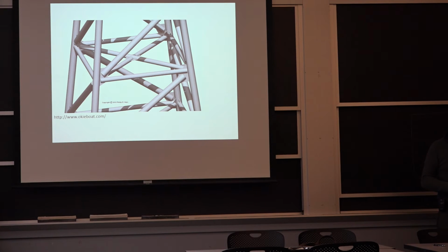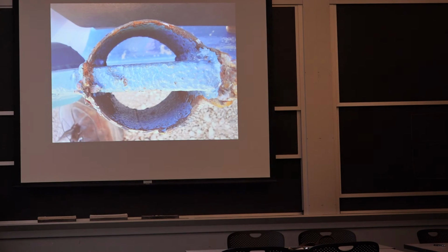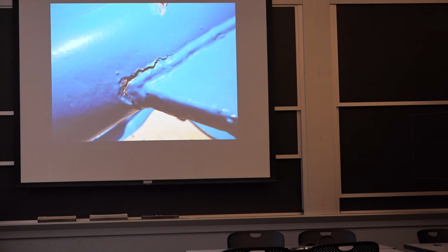Now, the people that put that segment of crane together didn't really understand all of it because they welded here the section that was in shear, but they also welded the top that's completely transverse to the weld. So they lost that ability to have a greater resistance in cyclic loading for the shear mode by just adding too much metal. There wasn't any good reason to do it because the ends of the tubes were open anyway.